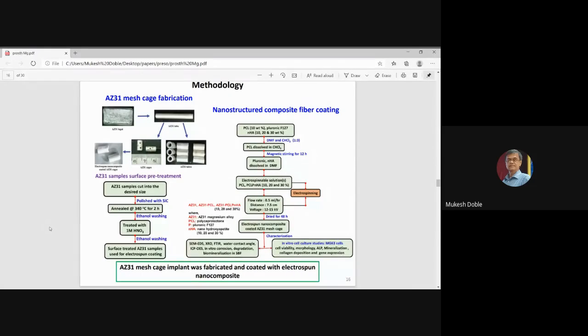Holes were drilled into that. So we ended up with the AZ31 magnesium cages. So we got from the ingots, we made the tubes, and then we created the cage, and then we electrospun polycaprolactone with hydroxyapatite and Pluronic acid. The idea is, number one, reduce the biodegradation of magnesium. Number two, improve the biocompatibility, because hydroxyapatite is part of the bone, so it will improve the adhesion of the cells and biocompatibility. That is how this particular thing is done.